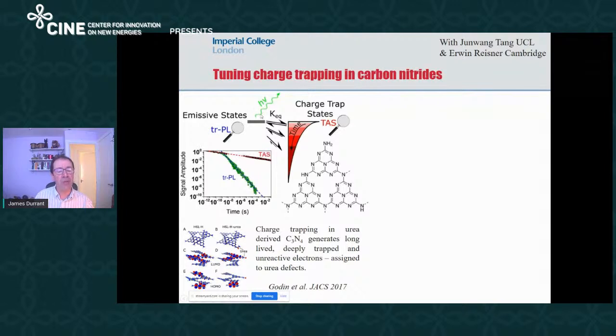But if we look at the equilibrium between those carriers and the emissive states where they came from, then the emission decays much faster. The way we understand that is that initially many of the carriers are only shallowly trapped and are able to be in equilibrium with the emissive states and so can emit photons. But over time, the shallowly trapped carriers, this is after our pulsed excitation, disappear, and we just get left with deeply trapped carriers. These deeply trapped carriers are entirely non-functional because they've lost so much energy they can't do anything.